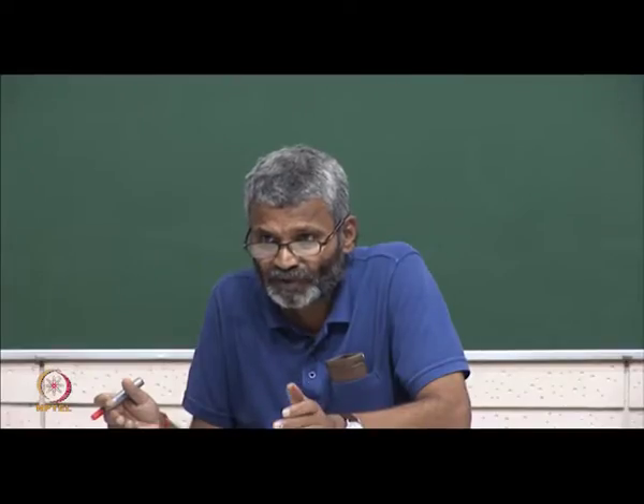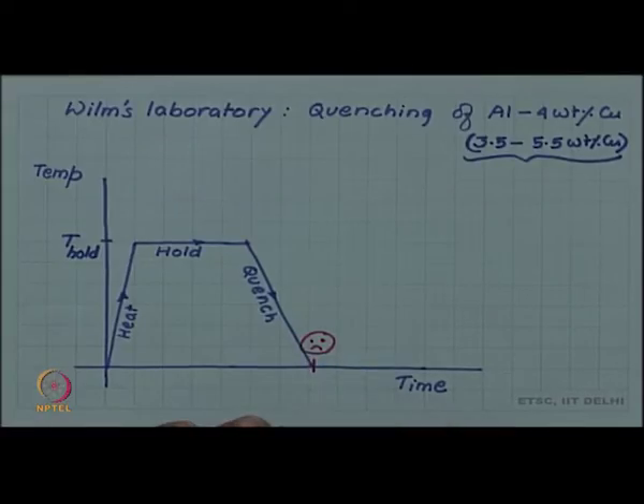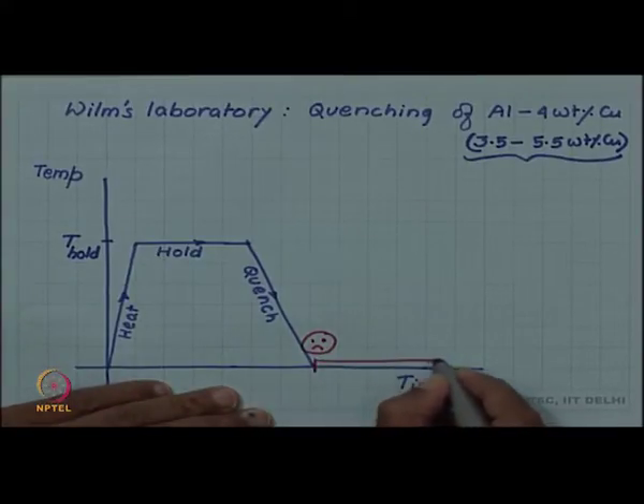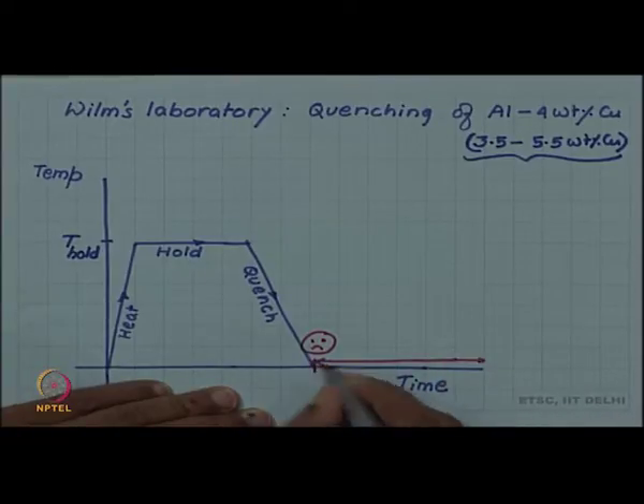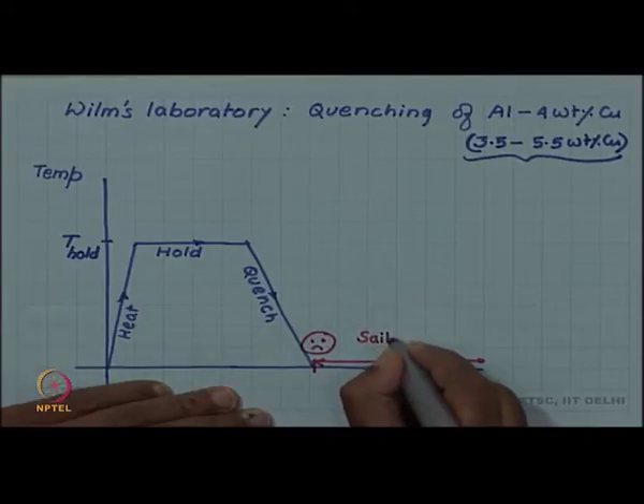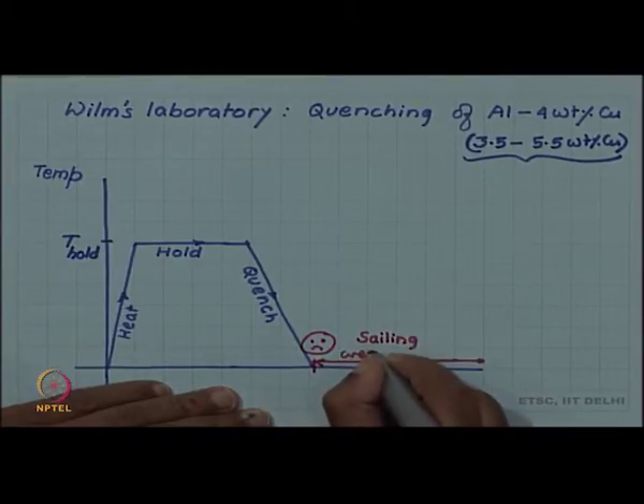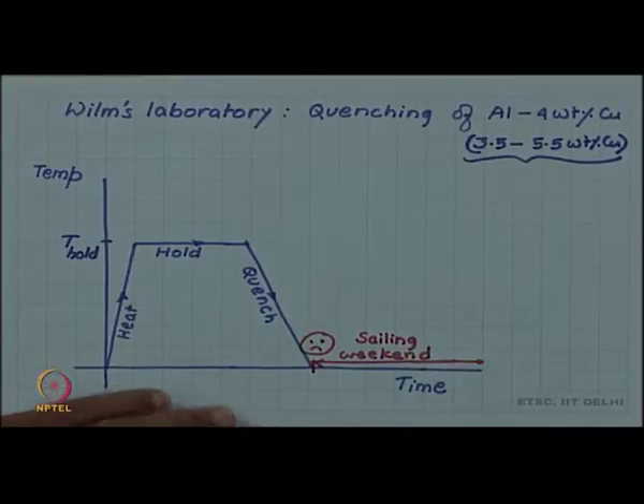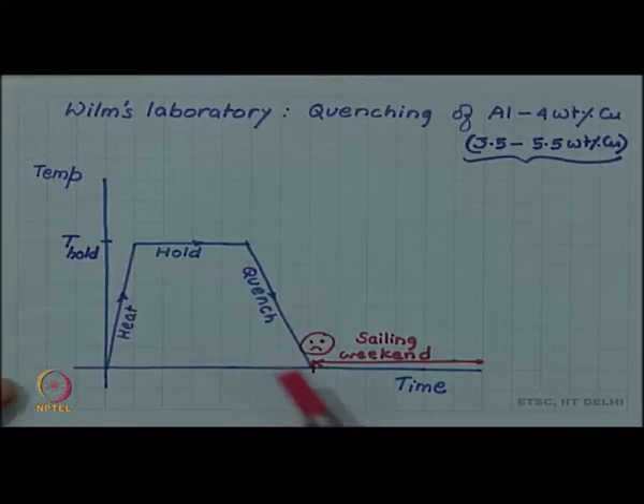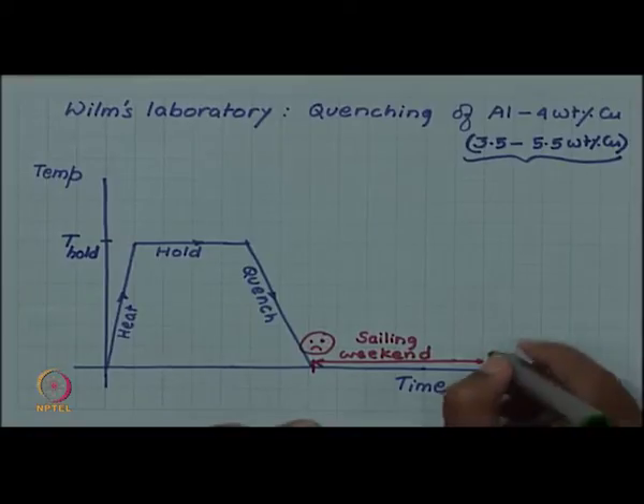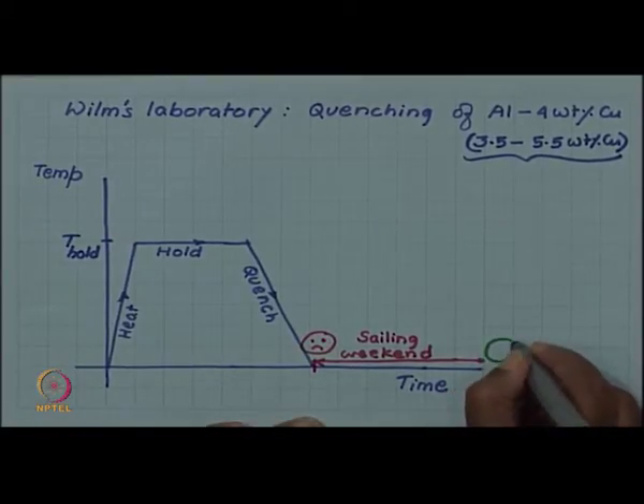Then it struck him, is it the weekend effect? Is it because he quenched the specimen on Saturday and is measuring the hardness on Monday, that is, he is allowing this period of weekend that hardness is increasing? So he did again a control experiment where he quenched and deliberately waited long enough time to measure the hardness, and he found that yes, hardness is increasing simply because of waiting.